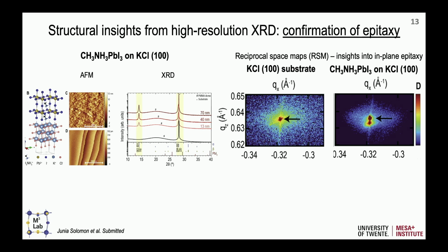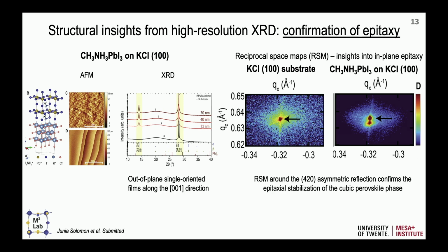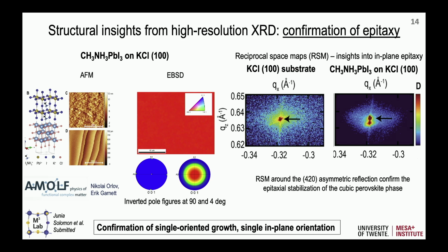And I will not have too much time to explain, but basically, a single point in this graph means it's a single crystal. This is the single crystal of the substrate. And then when Junia grows the MAPI on top, you see a little point just below. So it's showing that your MAPI layer, your perovskite layer, in this case 70 nanometers, is actually also single crystalline. Well, let's say single oriented. Otherwise you will see a line or something else. So that was a very nice thing to see. But what we wanted to prove, okay, this is just out of plane orientation, and this is confirming the epitaxial stabilization. So it's showing it's growing directly on top of the substrate. And I think there was a lot of discussion about collaborations. So here I would like to highlight that we also wanted to see how this goes on the film.